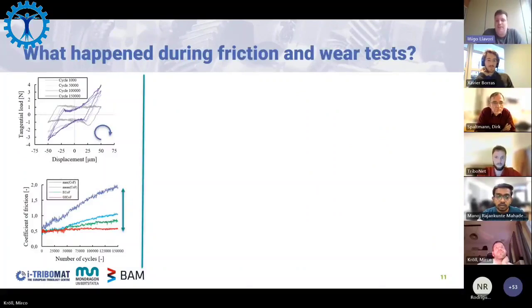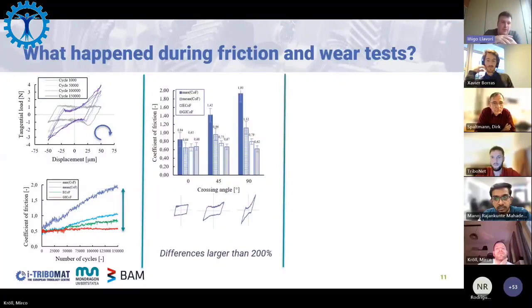So what happened during this friction and wear testing? In the upper side of the figure, you can see different friction loops that I recorded during different cycles. At the start of the test, you have a kind of flat-topped friction loop, but then during the test, this loop distorted a lot. You can see that the distortion is quite high.